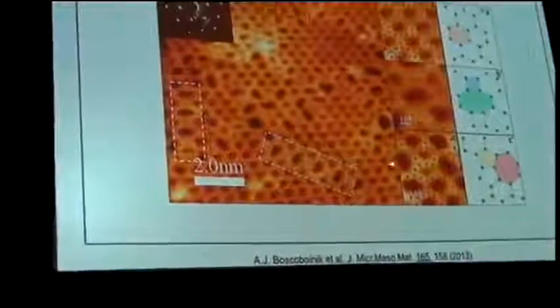And if you put aluminum into this, then all of a sudden this hexagonal structure is broken up, and you form these other ring structures on the surface. For example, this thing, if you would cut this out from this aluminum-doped structure and roll it up, it would give you a zeolite. So when you put the aluminum in, spontaneously there is a particular distribution of ring sizes induced.